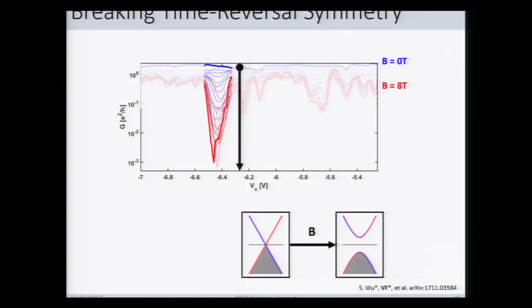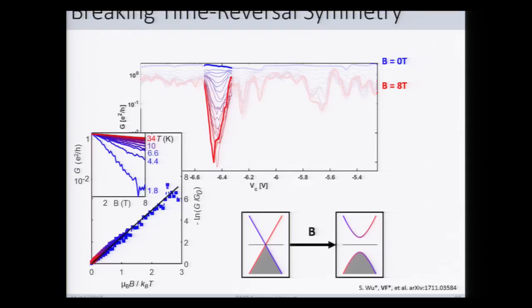So this would seem, in spirit, the right idea, that you have perhaps right here your chemical potential at the Kramers point, and then you can open a gap if your chemical potential is there. And indeed, we can take a line cut at a particular gate voltage and see that the conductance does indeed drop exponentially in the semi-log plot as a function of magnetic field. And moreover, as we turn on the temperature, we go hotter, this exponential reduction is reduced, as we expect for thermal activation over a semiconducting gap. So the typical thing to do here is to say, okay, we'll take an Arrhenius plot of the conductance. So this is the log of conductance versus 1/T. And then if we do it at every magnetic field, that would be a bit tedious. But instead, we say, okay, let's assume that our gap is linear in magnetic field and just put it here in the prefactor of the 1/T of the Arrhenius plot. And we find that all of the data points collapse onto the same trend. And that tells us that, indeed, we have exponential suppression with thermal activation where your band gap is linear in your magnetic field. And by doing this fit, we can extract an effective g factor for this orientation of magnetic field, which is about 5.